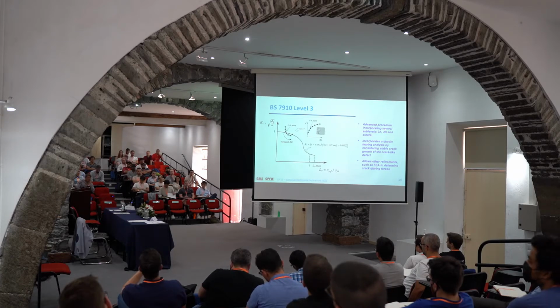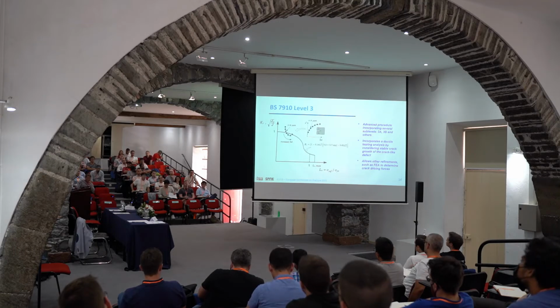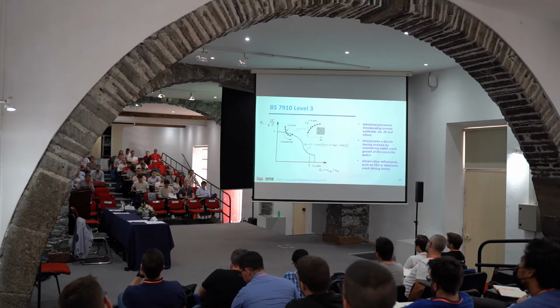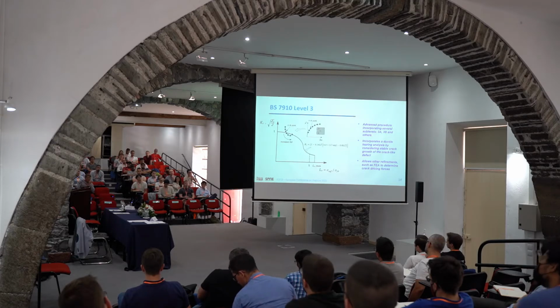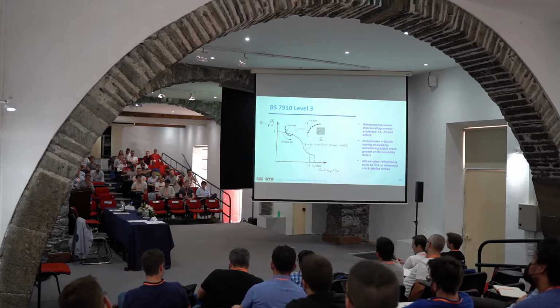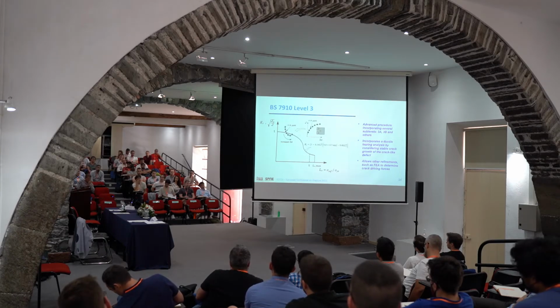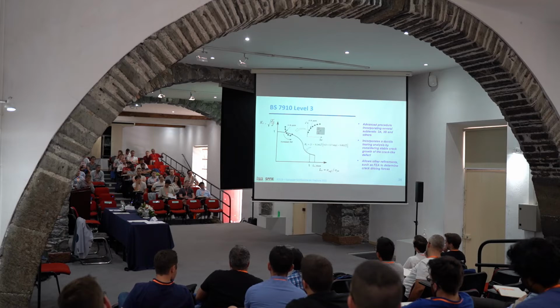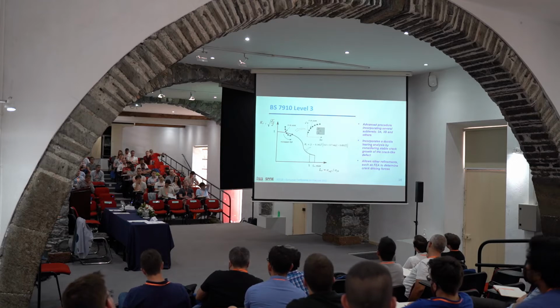Okay? The crack size can increase because of further loading. And I'm not talking about fatigue cycling. It's just because of overloading. Okay, the crack can increase in size. If the crack increases in size, I can take this into account, okay, by including a ductile tearing analysis of stable crack growth in the defect.